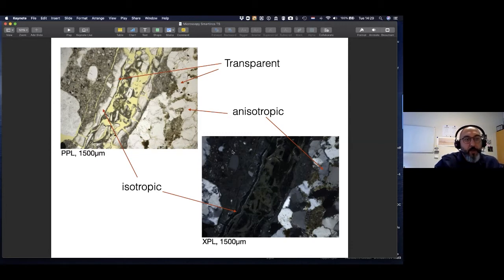And on the other hand, if you look at this aggregate, which is next to this crack, you see that it is formed by tiny grains of crystals. I can tell you these are quartz crystals. How do I know that these are crystals and not gel or amorphous phases? Because I can observe some colors in the cross-polarized light imaging mode. That's the only way I can tell that these are crystals. If they weren't crystals, they would have been observed like this, super dark.